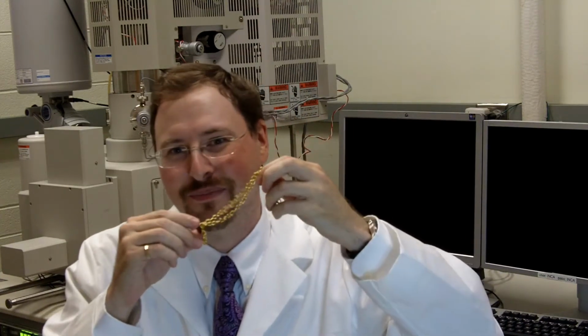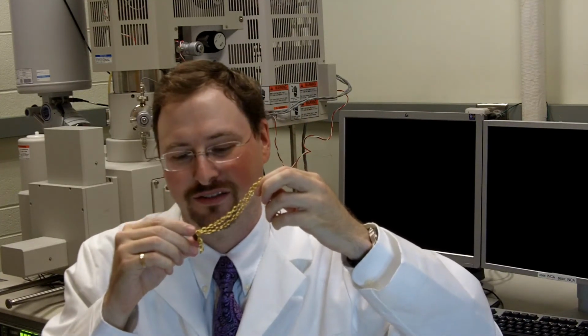Now let's look at this gold chain. Again, we can see very clearly using the backscatter detector a layer of something on the surface of the chain. But the analysis tells us that the chain itself is made from iron? What? If this chain was made of iron, I'm pretty sure I could easily attract it with this magnet. Okay, so the chain is iron, but the layer on the surface isn't.